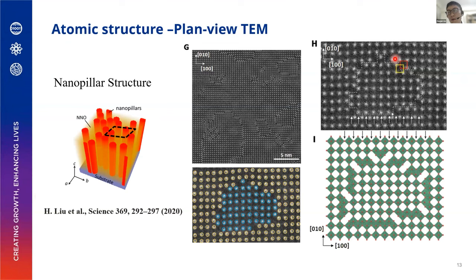So actually the ordering, especially at the boundaries, if you look at this figure, the ordering changes when you go to this pillar region. This position should originally be a sodium position, but what we see here are all niobium atoms, because the sodium is too light to be seen by this TEM image. So this should originally be a sodium position, but inside this region the niobium is actually occupying the original sodium position. So especially at the boundary, there's a change. I think it's chemically driven, stoichiometry driven. Because you have too many niobiums and not enough sodium in the system, the niobium has to go somewhere. It can go to the original sodium position.